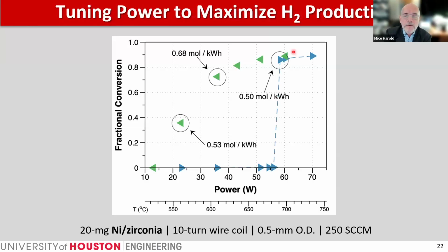Now, interestingly, before I get to some mechanistic aspects, if one calculates the moles of hydrogen produced per kilowatt hour supplied, which Elmer has done, it's interesting to note that there's a kind of maximum utilization of the provided electrical energy, through Joule heating, that maximizes the production of hydrogen along this high branch. Too high of a power leads to diminishing returns as the conversion approaches completion. Too low of a power does not produce enough hydrogen. There's actually a sweet spot where one gets a nice balance, or a maximum in the hydrogen production or energy utilization.